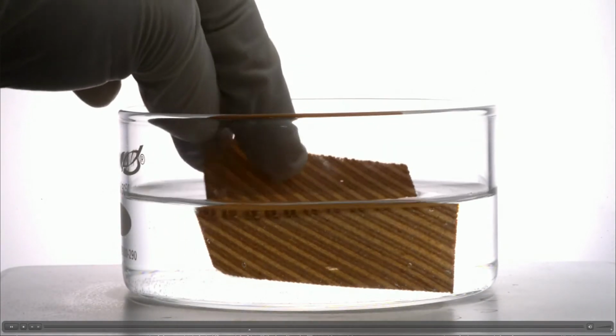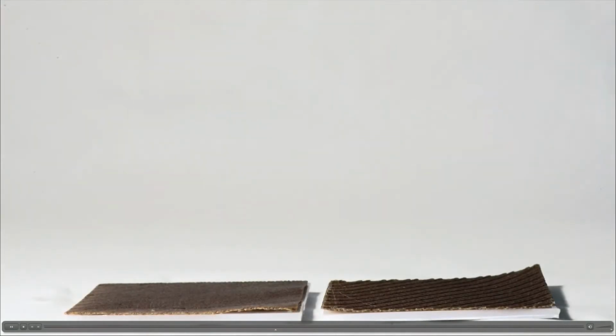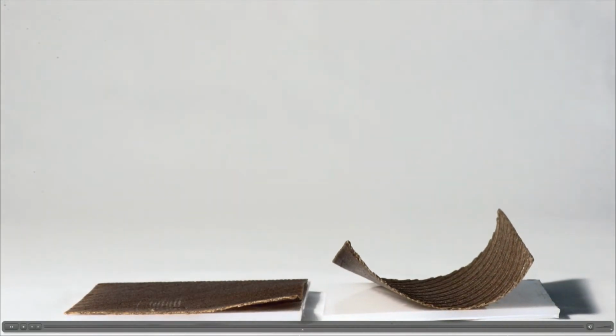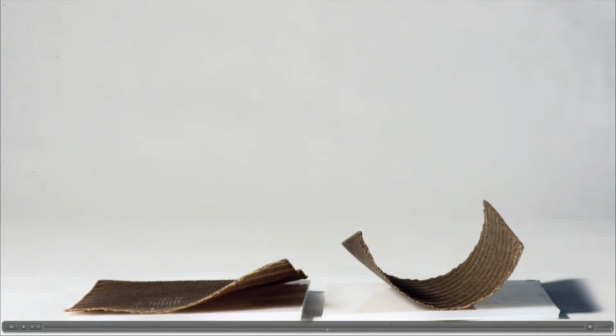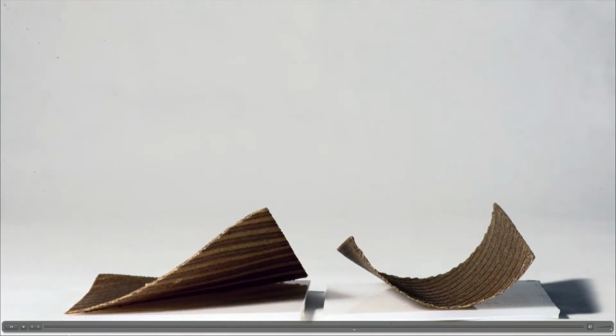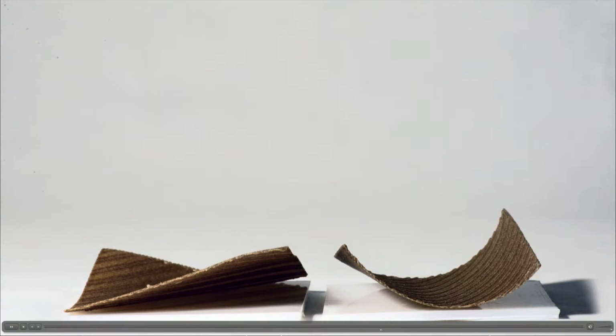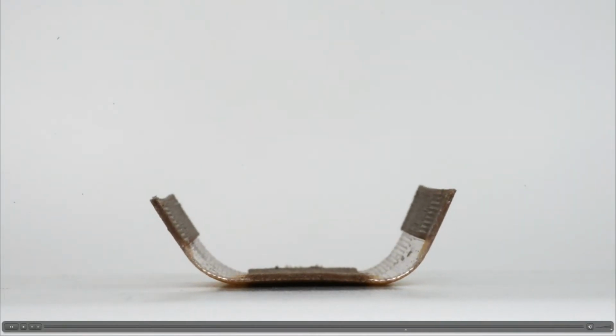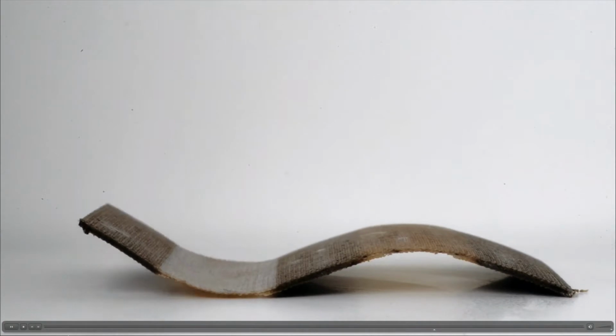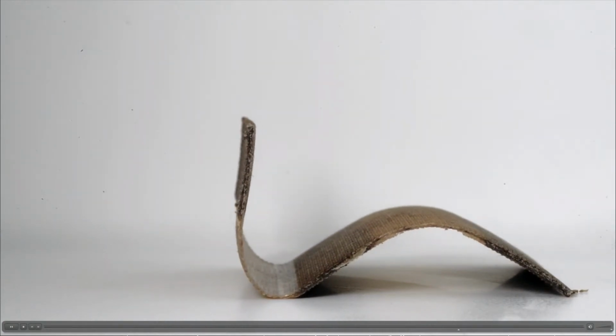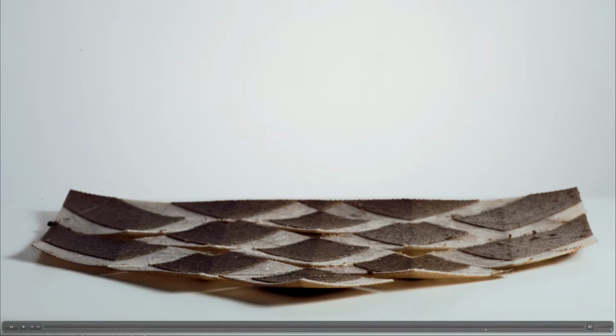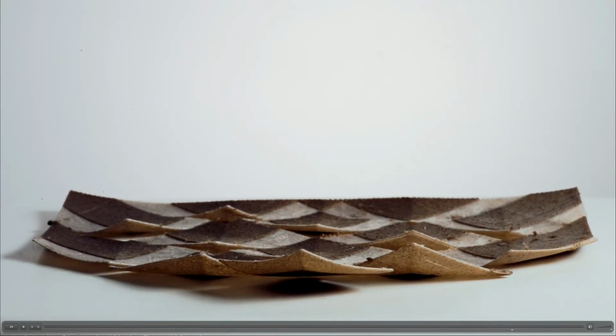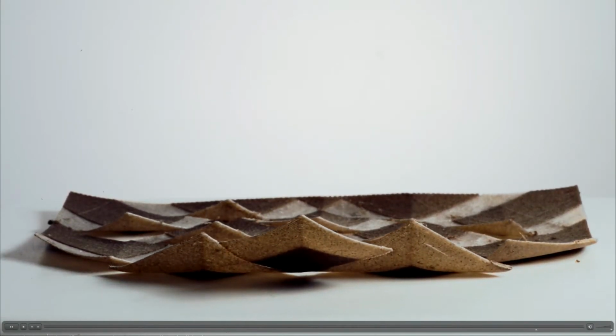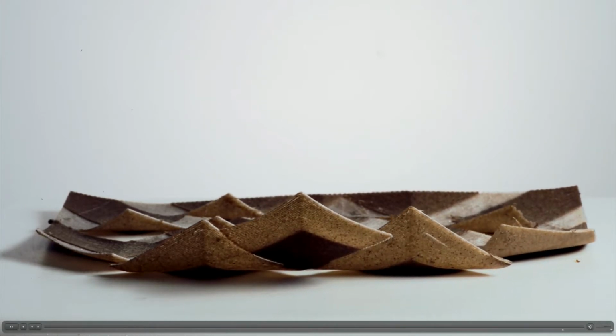You either submerge them or you change the moisture in the environment, and the different grains will create different behaviors in the wood. So you can get twisting, or you can get rolling, or you can get curling, all different types of angles and curvature. You can get wood that folds to 90 degrees. You can get wood that turns into furniture-like shapes. You can have wood that turns into fish scales. Wood that does things that you would never naturally find, like converging, diverging grains, 2D and 3D structures of wood grain that would never naturally occur. You can even get elephants that fold.